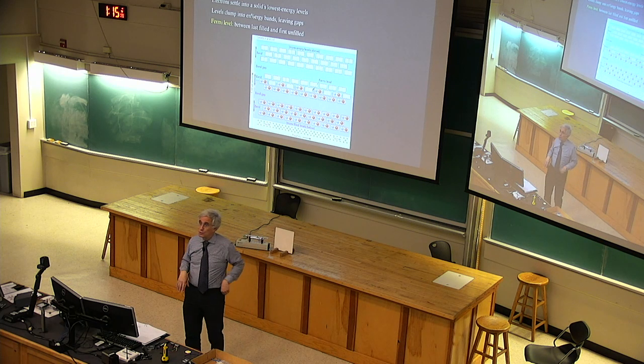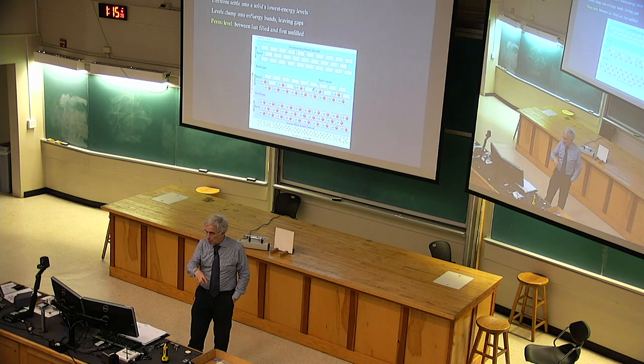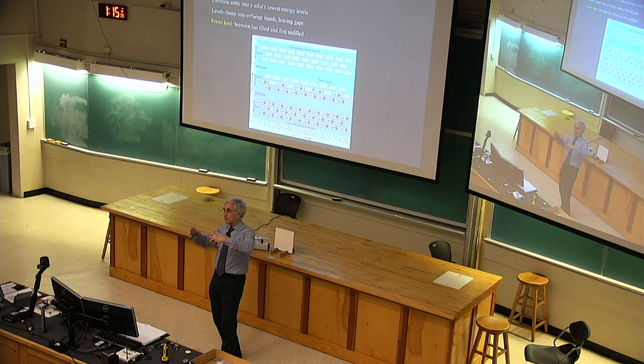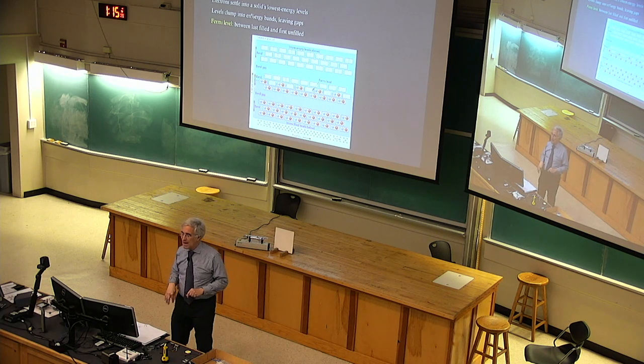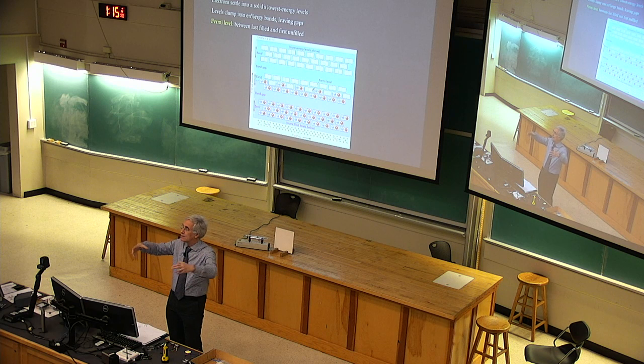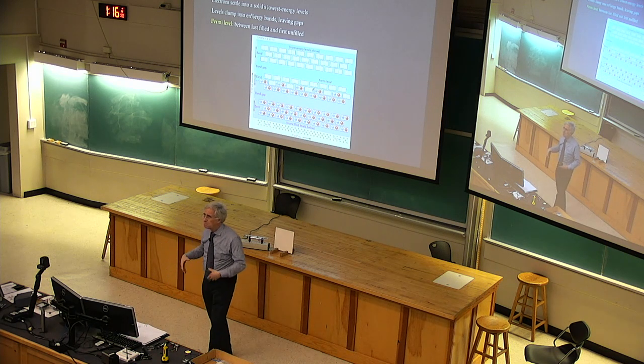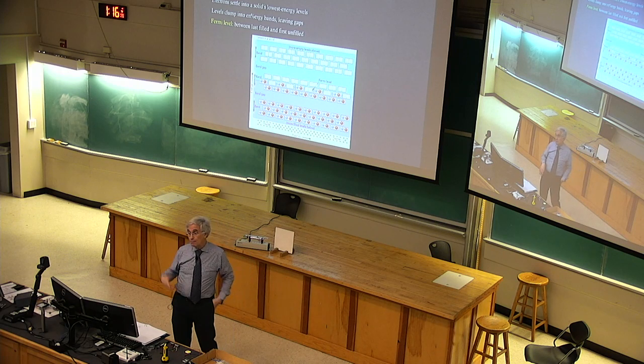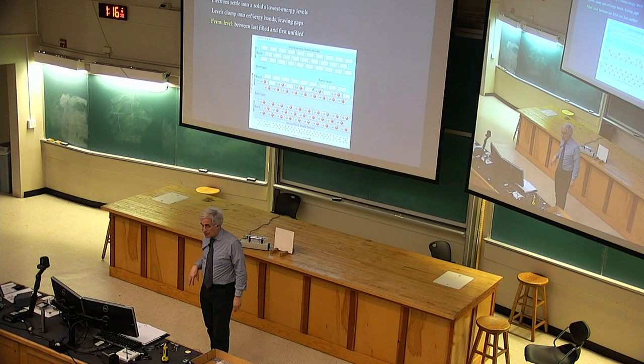It comes as close as it can, the wave does, the strength of the wave comes as close as it can to all the positively charged nuclei, so that's good. That reduces electrostatic potential energy. And the wave also has crests that are as widely spread, as big wavelengths as it can get. And I told you several times now that the kinetic energy of the electron is associated with the spacing between crests, the wavelength. So it can minimize its energy by finding a wave that's close to the nuclei and that has big wavelengths. And it will spread out across the entire solid, in principle at least.